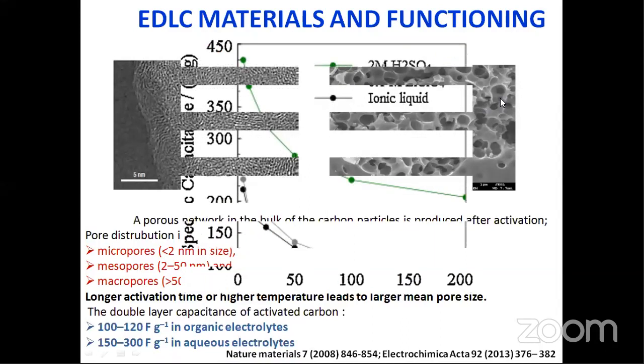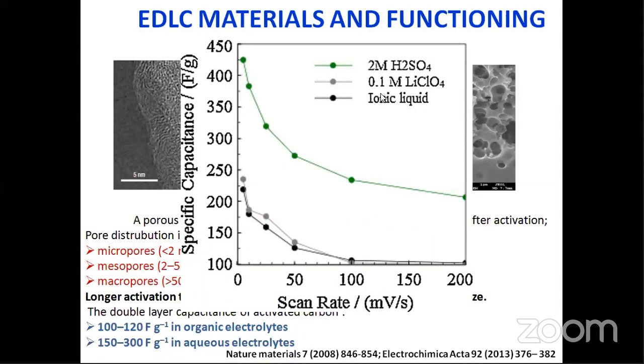Say, for example, if you use carbonization materials in different electrolytes like 2 molar H2SO4, 0.1 molar LiClO4 and an ionic liquid, look at here, we have achieved 2 times higher capacity. So it is a high capacity, the carbon material has 2 times higher capacity than in the other aqueous systems.